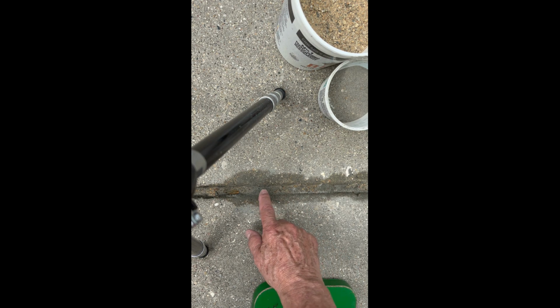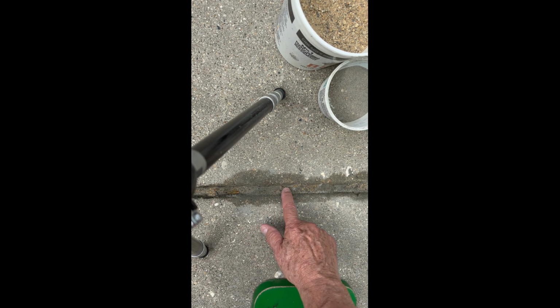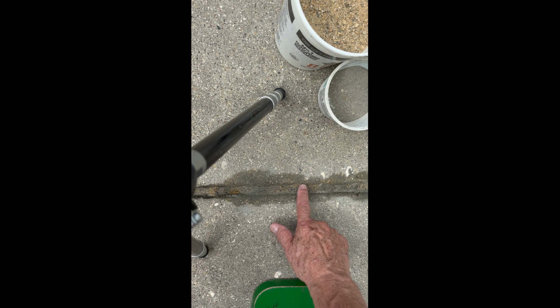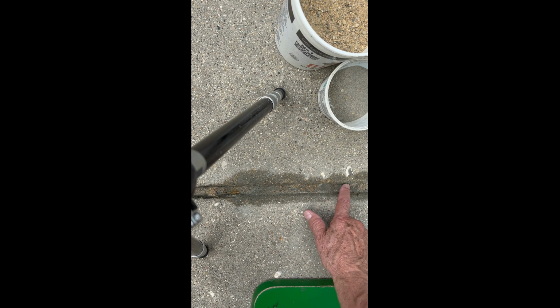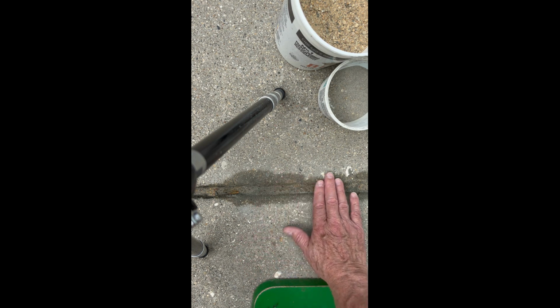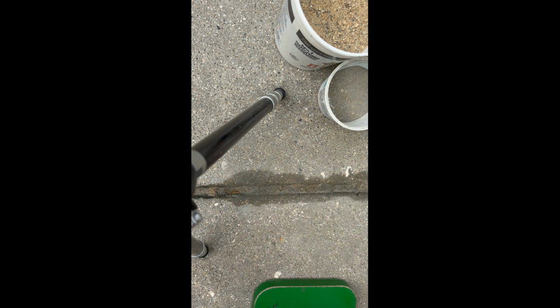Within an hour or so, the mixture will set, as shown in this second video. Check to see that it is hard. If not, adjust your mixture, likely adding a bit more concrete patch to the mix proportions. However, too much concrete patch in the mix will likely harden and shatter over the course of seasonal weather changes. Therefore, make and keep a record of what, where, and how much you used during your application.